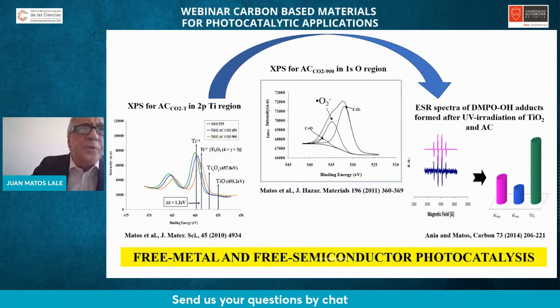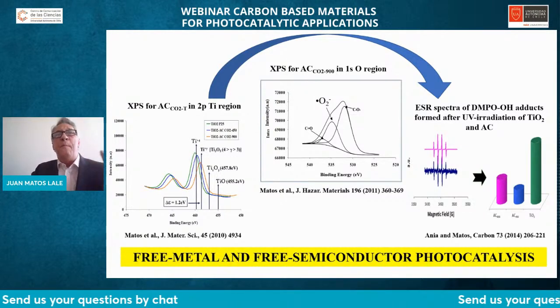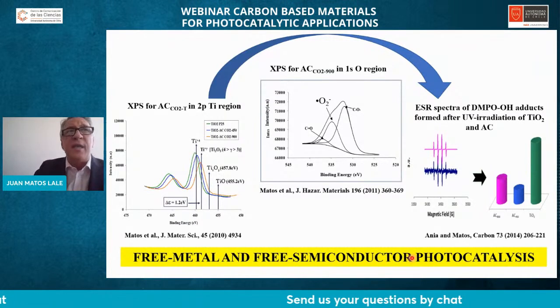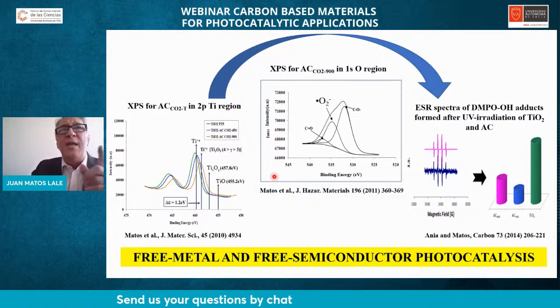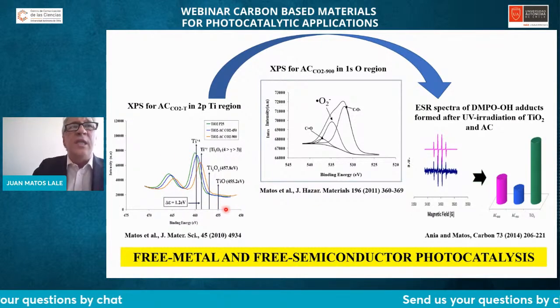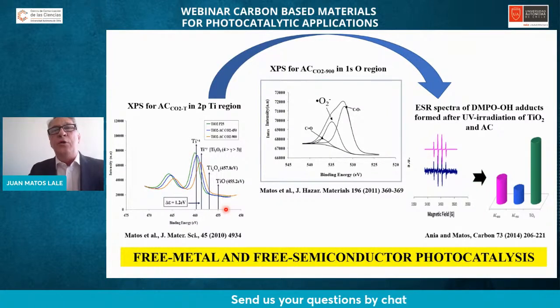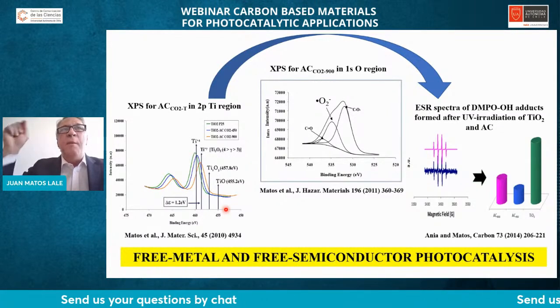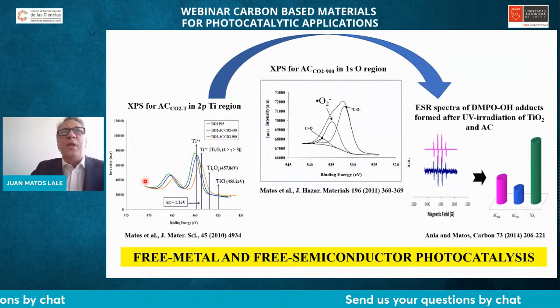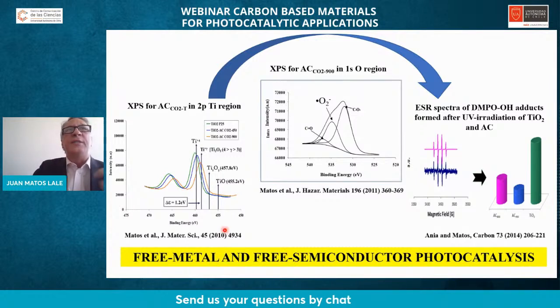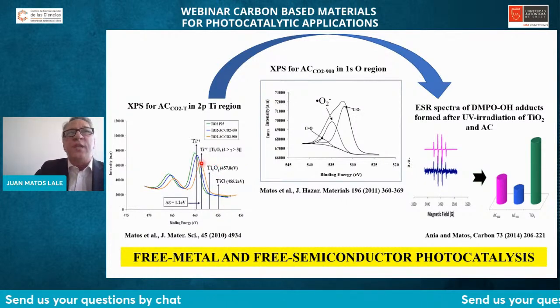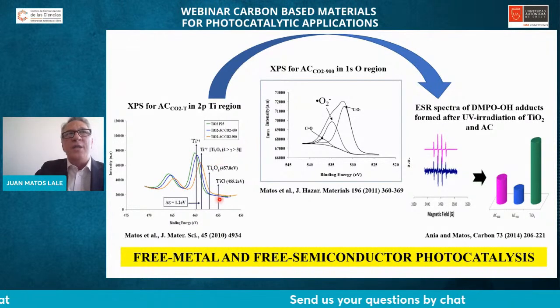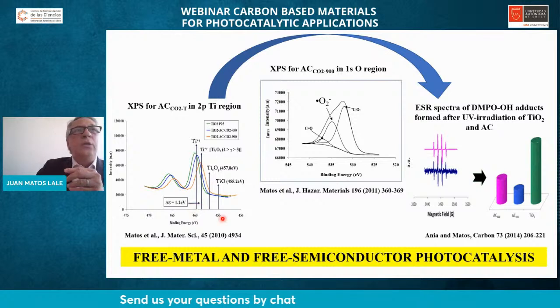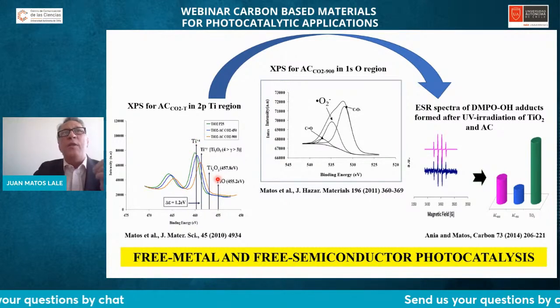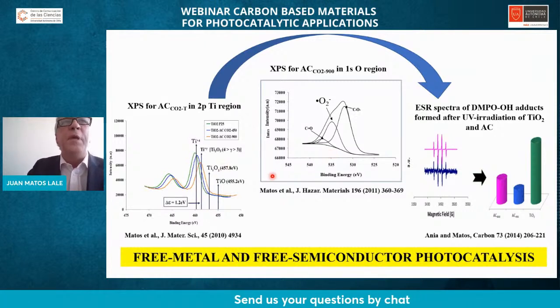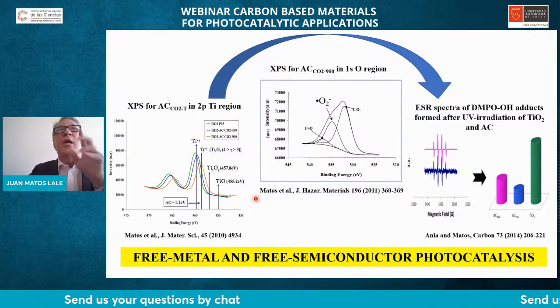So, more importantly, in very recent work, we are dealing with the free metal and free semiconductor photocatalysis concept. And this is because we are able to demonstrate that carbons are not only coordinated by means of the functional groups and the sulfates to the titanium atoms in the vortices of the octahedra of titanium dioxide. But we proposed the formation of a non-stoichiometric titanium oxide in the shape of titanium 3, oxygen 5, because the coordination was unable to reduce titanium 4 to titanium 3. So it means that the real photoactive species is not titanium 3, is not titanium 4, is titanium between 3 and 4.